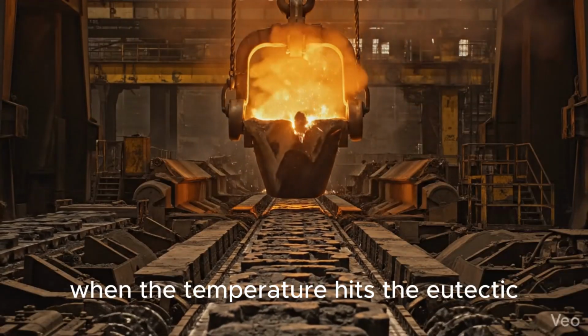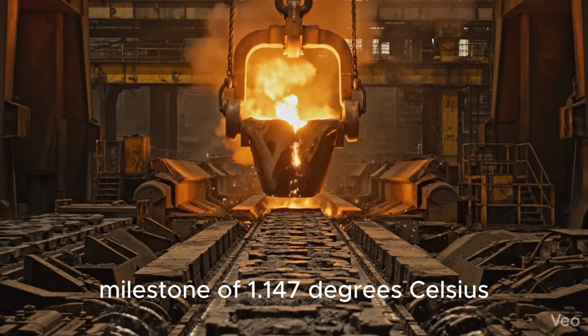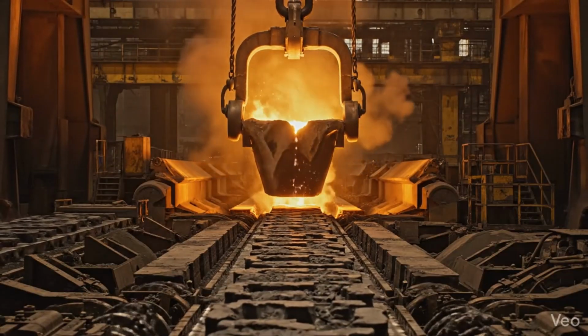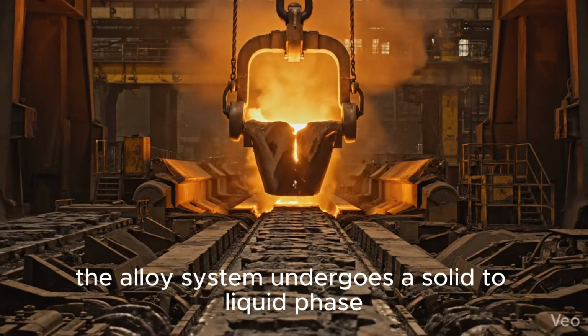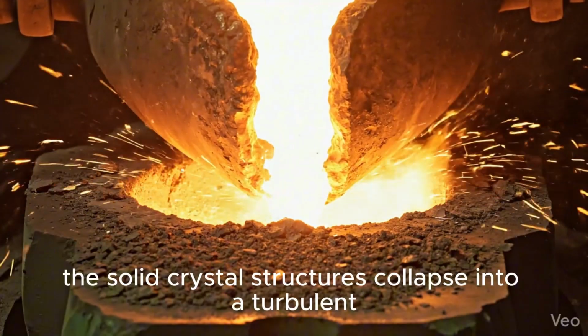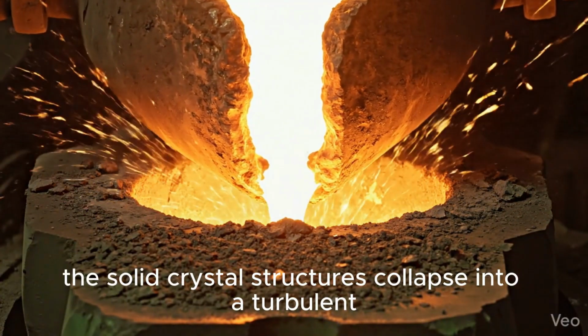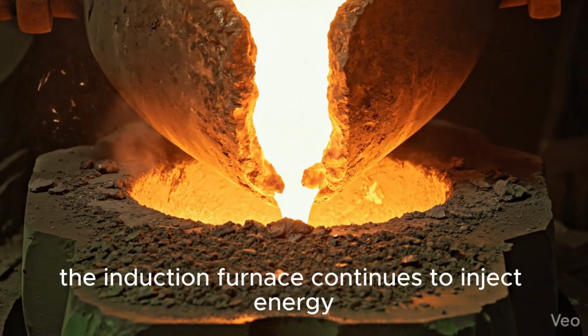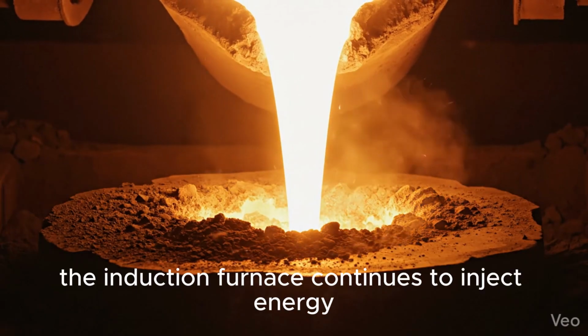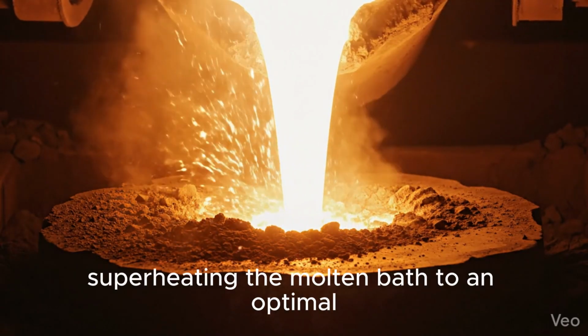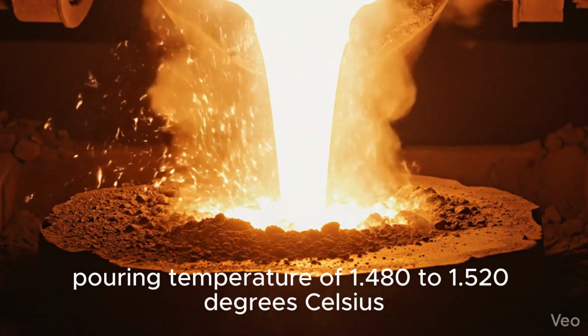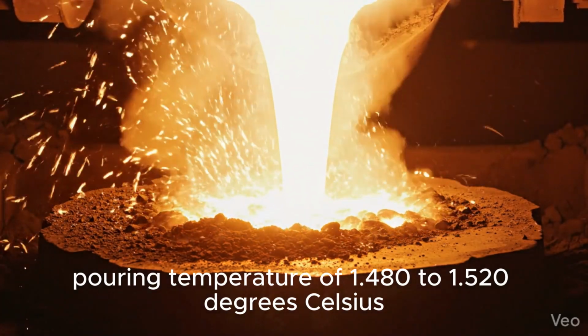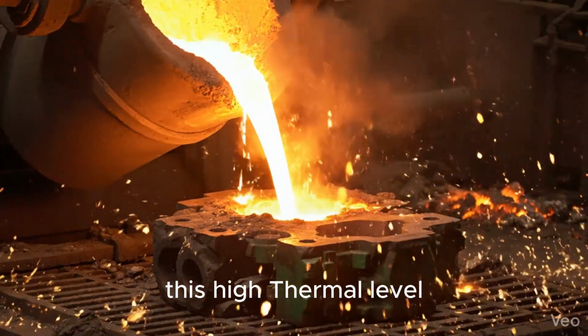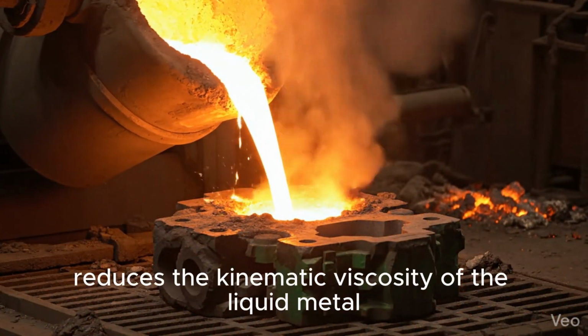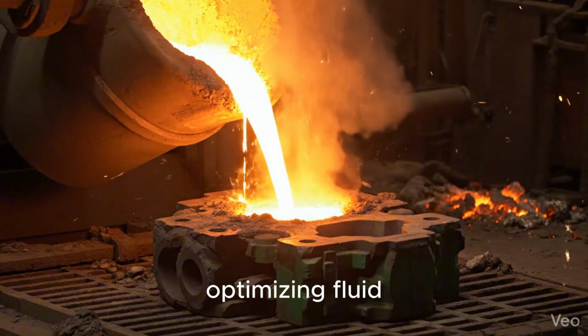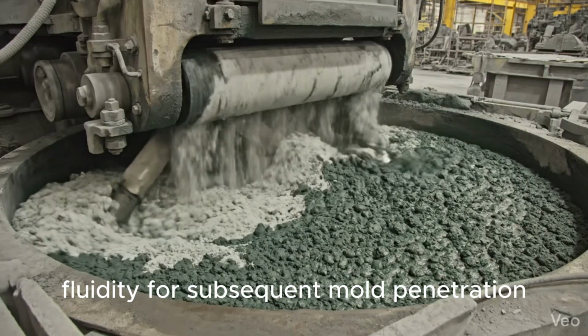When the temperature hits the eutectic milestone of 1,147 degrees Celsius, the alloy system undergoes a solid to liquid phase change. The solid crystal structures collapse into a turbulent molten state. The induction furnace continues to inject energy, superheating the molten bath to an optimal pouring temperature of 1,480 to 1,520 degrees Celsius. This high thermal level reduces the kinematic viscosity of the liquid metal, optimizing fluidity for subsequent mold penetration.